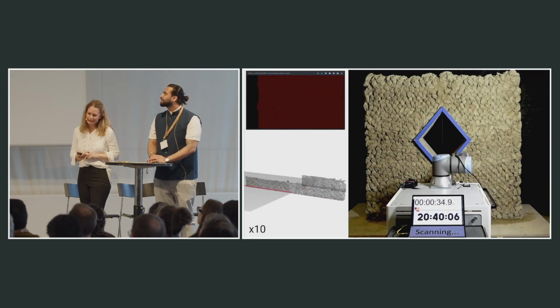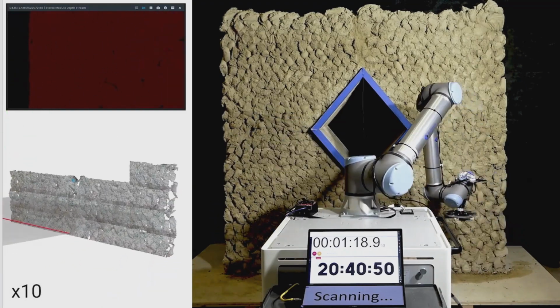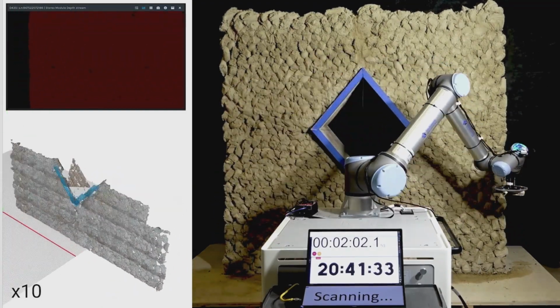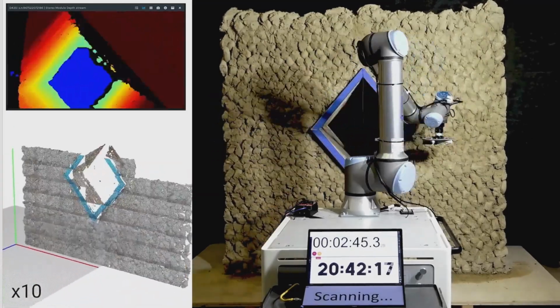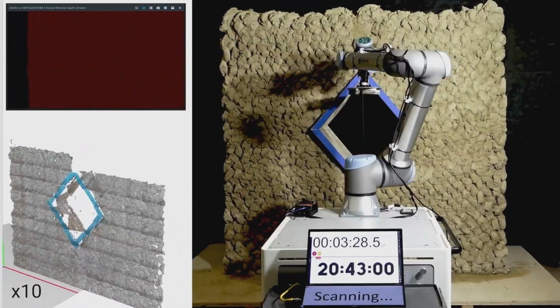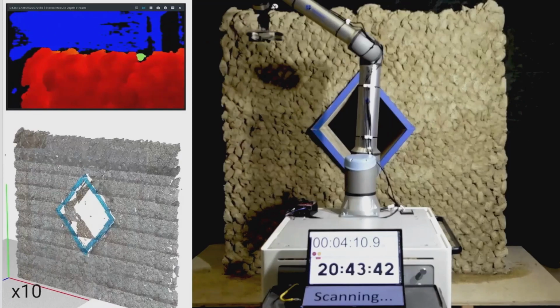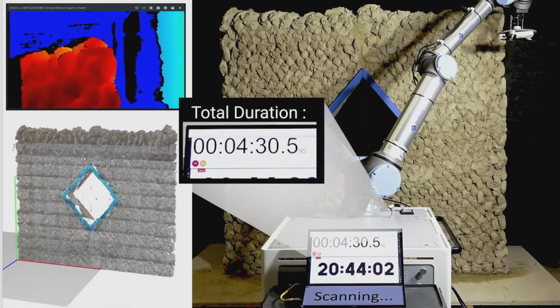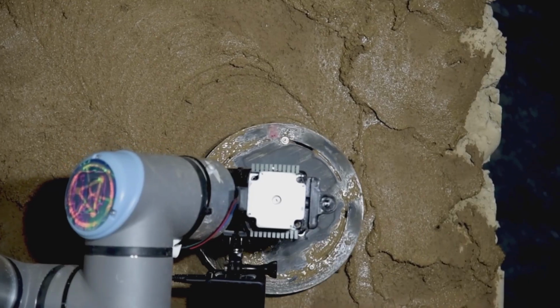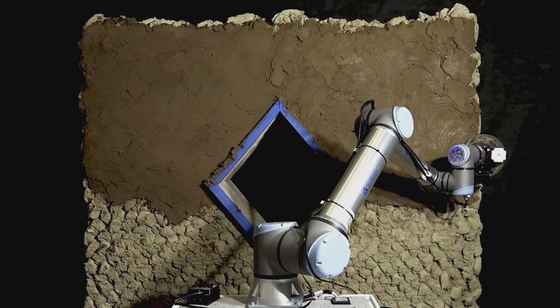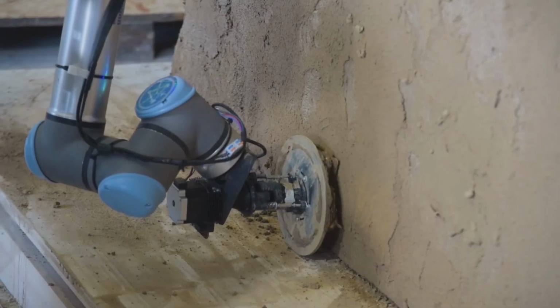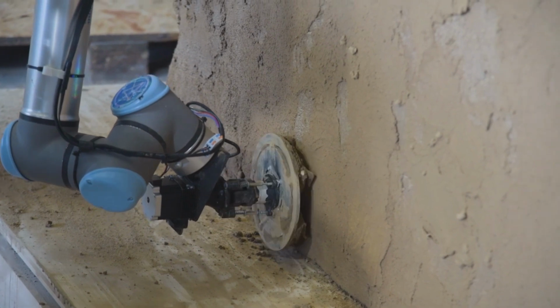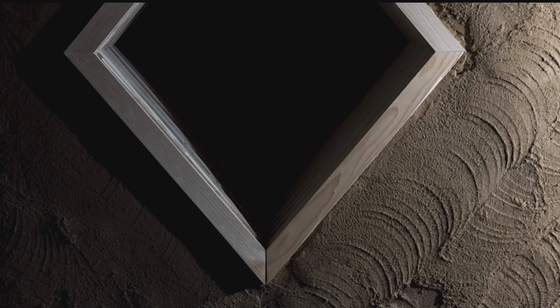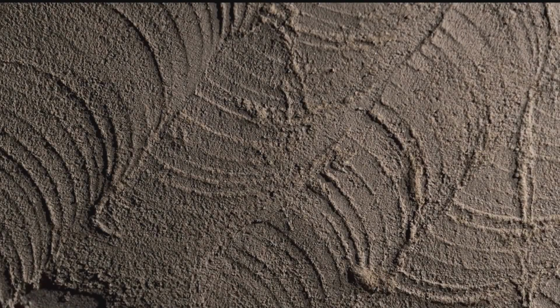And also in the context of MAS, with 2 of our master's thesis students, we developed another robotic surface finishing method. First, we acquire the surface geometry because it's very textured, and then we use a compliant robotic surface finishing tool to apply a clay-based plaster on the surface. And this gives us a lot of processing possibilities because we can basically take a very cheap infill material, and we can use a very fine, high-quality material on the outside, and we can manipulate the vapor permeability or the durability by